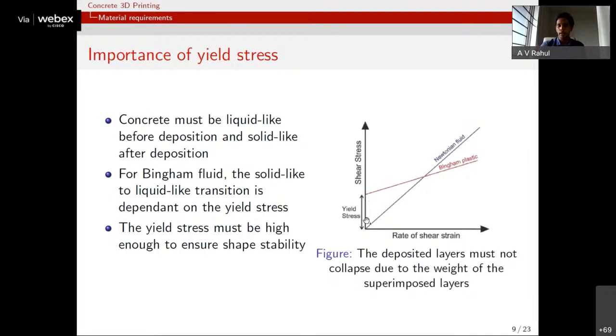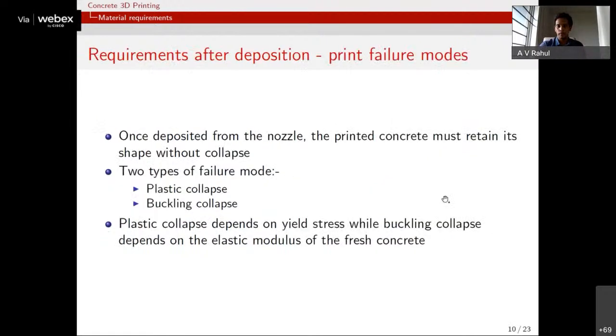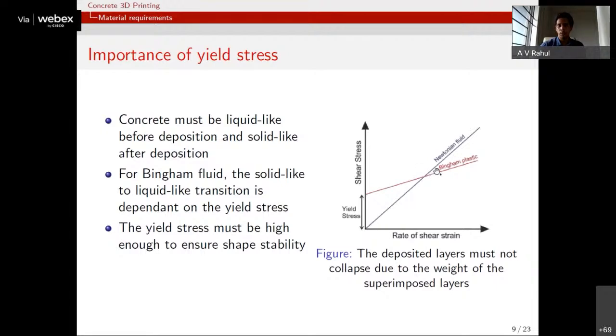Now, once the flow has started in the material, the slope of the graph dictates the resistance to flow, which we call the viscosity of the fluid. So the slope of this line determines the viscosity of the Newtonian fluid, and the slope of this line dictates the viscosity of the Bingham plastic fluid. To design concrete for 3D printing, to have that shape-retaining characteristic, we have to design concrete to have a high yield stress. For conventional concrete, you would normally have a yield stress of around 200 to 300 pascals. But for printable concrete, you have to have a yield stress of about 1,500 to 2,000 pascals, about an order of magnitude higher than conventional concrete.